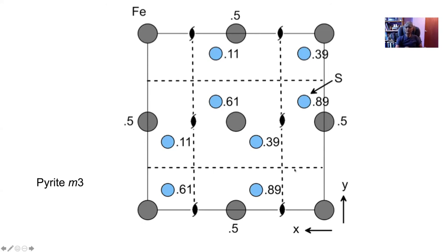So in this case, if I take this atom at 0.39, I reflect it to this position here, and then translate by a distance which is half the unit cell, then I recover the position here. Because there is just one translation involved, and it's a glide by half the unit cell, we call this an a-glide plane. But we'll come to that later. If I don't include these translation elements, then I won't be able to correctly predict the structure.